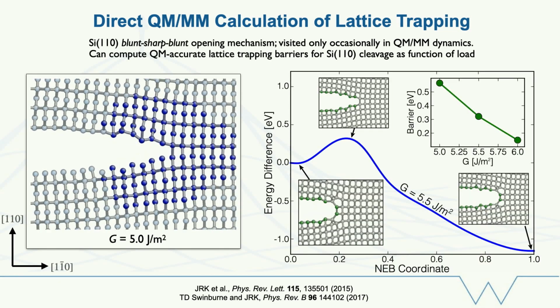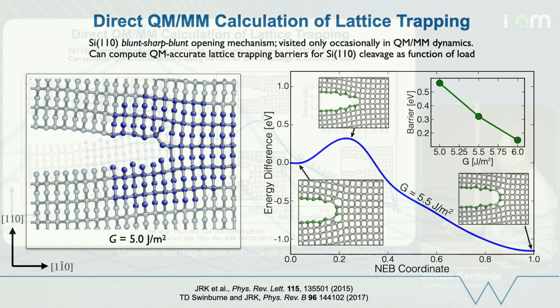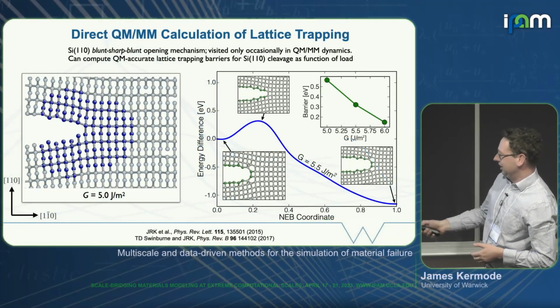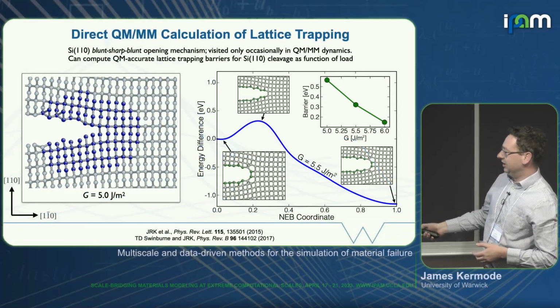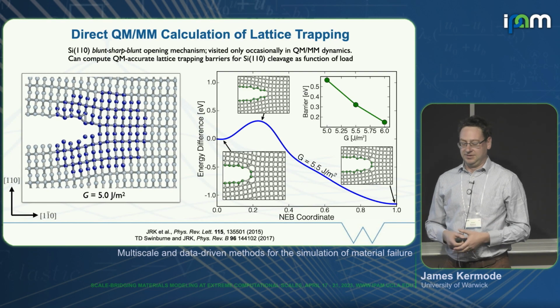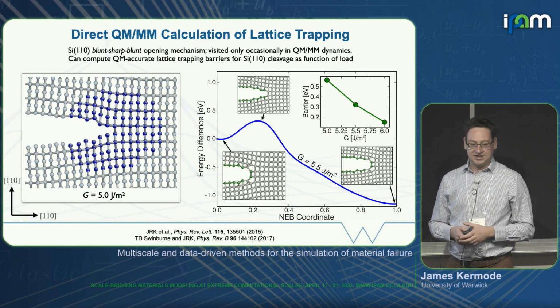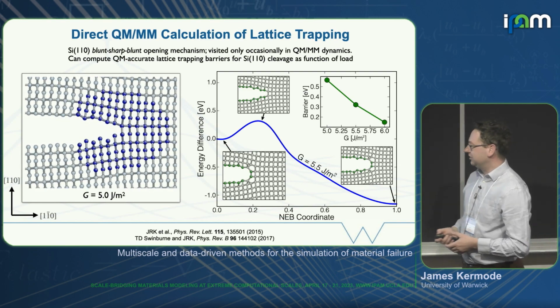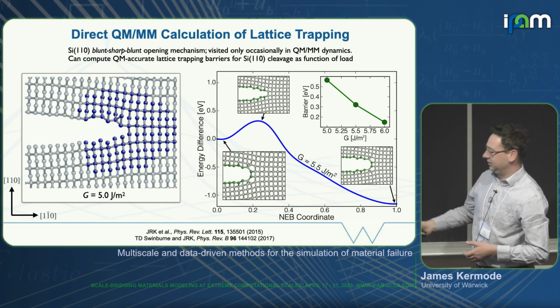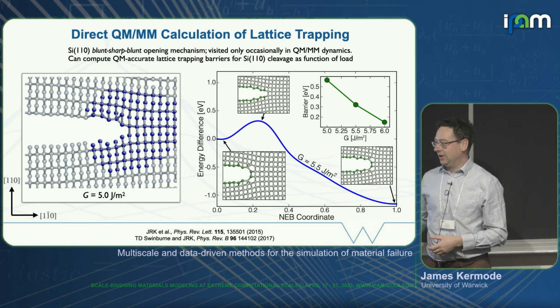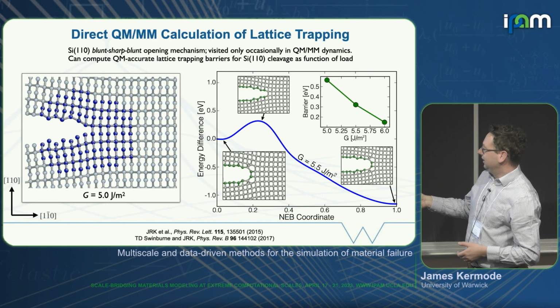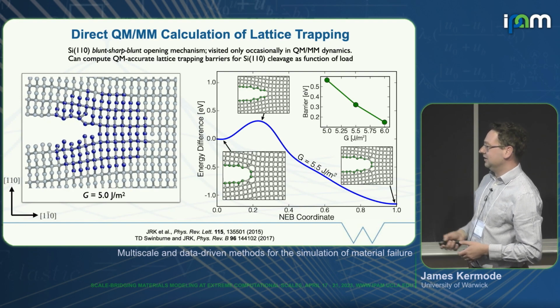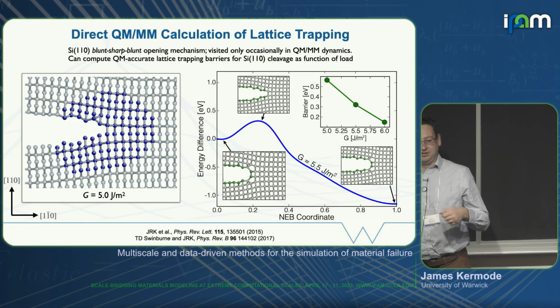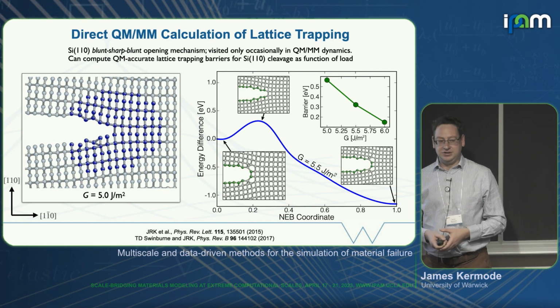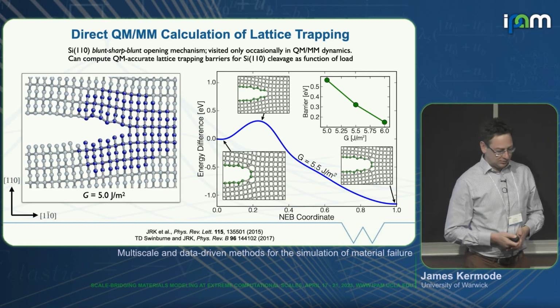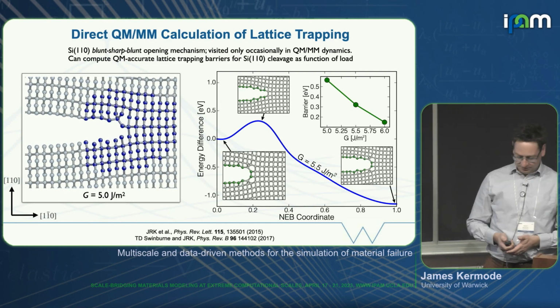So together with Tom, we did this a few years ago. We can relax configurations, we get minima, and then we can join those minima with a chain of states and relax using what's called nudged elastic band to get a minimum energy path for this process, still using quantum mechanics near the crack tip and a classical description far away. We can then repeat that at a variety of different loads and see how that lattice trapping barrier goes down as you pull harder, and find the range of stable loads at which the crack is metastably trapped.